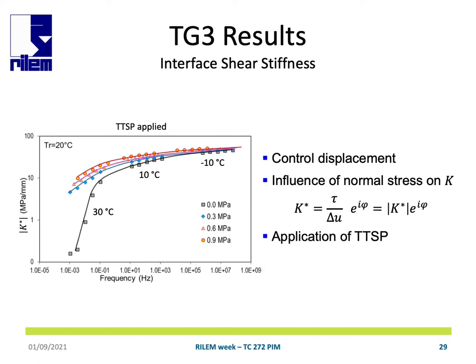Interface shear stiffness increases with normal stress level. Moreover, frequency and temperature sweeps allow to show that a time-temperature superposition principle can be applied on the shear interface stiffness by building master curves.